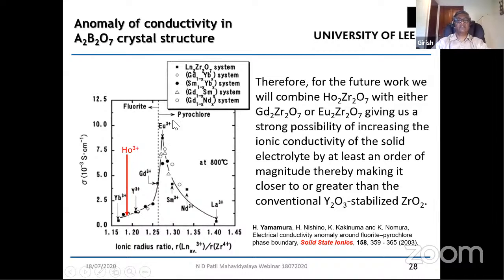And if this graph is a true representation of the fluorite and pyrochlore phases of the rare earth systems, whether zirconate or hafnate, then there is a good likelihood that this material would surpass the ionic conductivity of yttria stabilized zirconia and will be very close to the ceria gadolinia type of electrolyte. Now, what is the advantage?